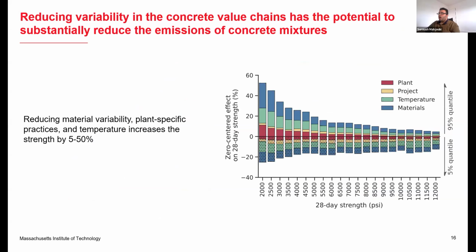We were also able to find out and quantify the impact of plants, projects, temperature, and materials variations on mix codes. So we considered the 5% quantile, which represents one of the worst case scenarios for the quality of operations, and the 95% quantile represents the best quality of operations. And we could see that these variations have an impact on the 28-day strength too. So by reducing the material variability, plant-specific practices, and temperature variations, we can increase the strength by 5 to 50%. And this impact is higher for lower strength mixes. As you can see here, for example, for 2000 psi, we can improve the average 28-day strength by removing these variabilities.